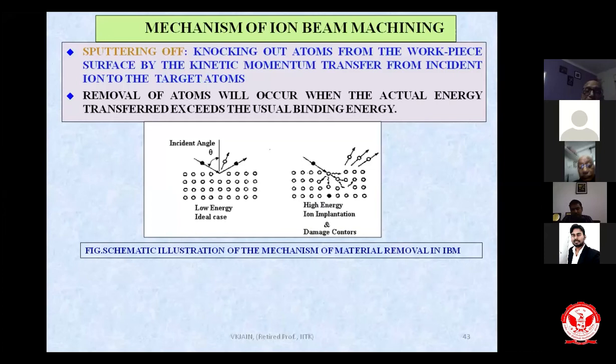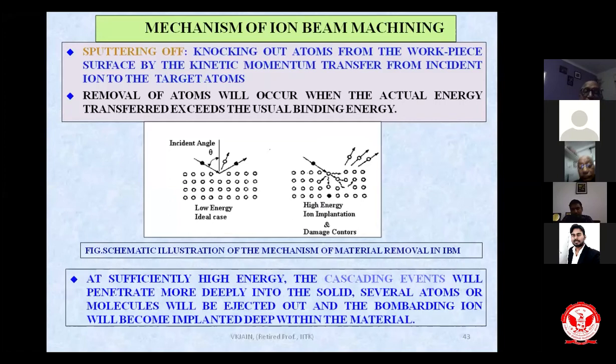Now, what it means is that at sufficiently high energy, the cascading event takes place. Events will penetrate more deeply into the solid. Several atoms or molecules will be ejected out, and the bombarding ion will become implanted deep within the material. That is what I have shown to you: the implantation by one ion, and more than one atom being displaced or removed.